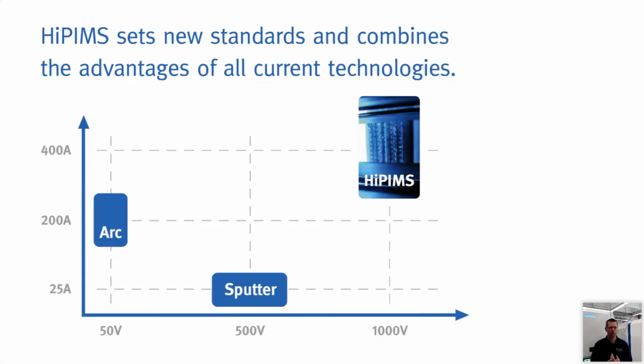The other technology is sputtering. The same thing happens here like in a light bulb. You take a target and you bombard it with gas ions, and you take the material out atom by atom. The big thing in HiPIMS is high impulse sputtering. You do sputtering with way more energy in the pulse. So you take the advantage of sputtering, a droplet-free smooth coating, and you apply more power, which helps you to increase adhesion of the film. And here I think we have a very nice animation to show you the differences in the technologies.